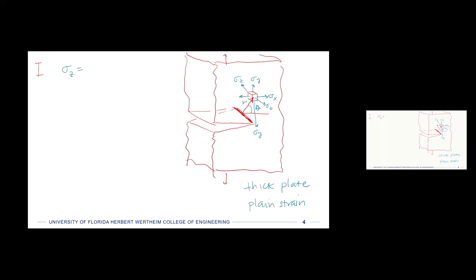So let's write down expressions for sigma x and sigma y. So sigma x is going perpendicular to the loading direction. So this is mode 1, so we'll have K, big Roman numeral 1, divided by the square root of 2 pi r. And then we'll have some terms that have to do with the angle, right? And so it's just some longer terms. So we'll have cosine theta over 2 times 1 minus sine theta over 2 times sine of 3 theta over 2, the product of those, plus some sigma x, if there is any in the far field, plus what I'm going to write as order, so this O in parentheses, of the r to the 1/2.